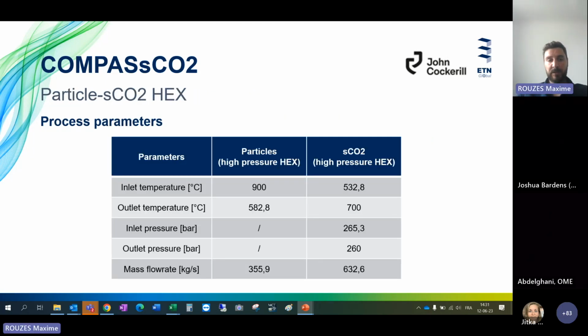So here we're talking about this kind of heat exchanger. On one side, on the particle side, you have the inlet temperature at 900 degrees C and the outlet around 600. And on the sCO2 side, it goes the other way around. The sCO2 is heated up from 530 degrees up to 700 degrees C. We want to increase the temperature because it also increases quite significantly the efficiency of the sCO2 Brayton power cycles, going up to, in the case of Compass sCO2, 49%. And all that is being done at high pressure as well, around 250 bar.